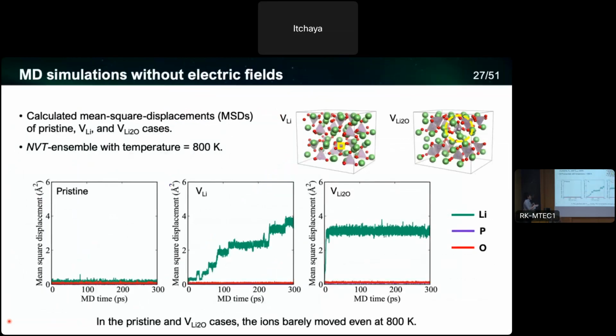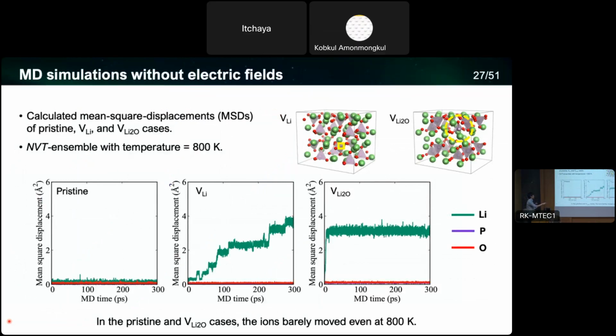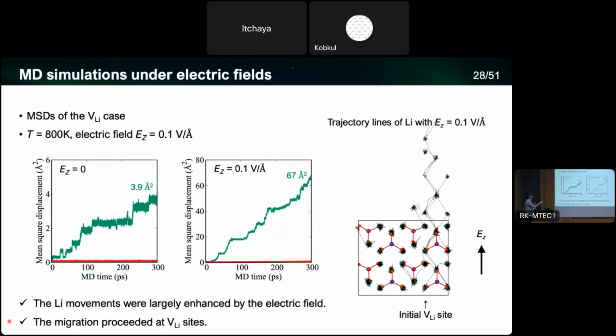So this one is without electric field, but the models we consider are the lithium vacancy model and also the Li2O vacancy model. And this graph shows the mean square displacement as a function of molecular dynamics time. So in the pristine case and the Li2O vacancy case, the lithium mean square displacement is flat. So we ignore these cases because these are not mobile. And in the case of lithium vacancies, the lithium mean square displacement gradually grows, suggesting that the lithium is hopping through the vacant site. So we then perform molecular dynamics with electric field.